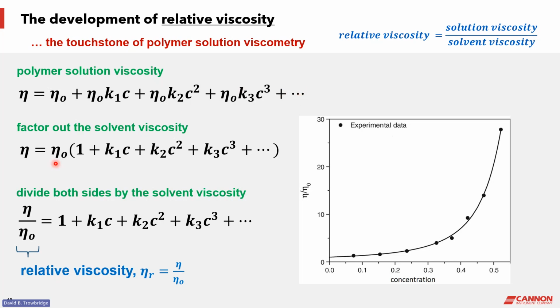So the first thing we can do is take the viscosity for the solvent out of each of these terms. You can see it appears in each one, but we factor it out, and then adjust the remaining terms to be without it. And then we're able to divide both sides of the equation by that solvent viscosity, and here we have the form for the relative viscosity, written here with a typical notation of eta with a subscript of r for relative. And the terms are just carried over from the parenthetical section of the previous equation. So this is the equation for relative viscosity, and this is a graph of what you would find.